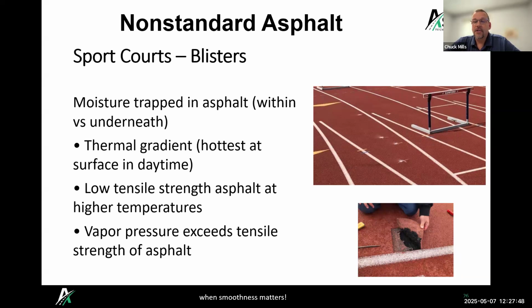So a lot of these coating systems are multi-layered coating paint systems that seal up the air voids at the surface of the asphalt. So if there's any moisture in the asphalt or underneath the asphalt, it can't really escape. And if we don't have proper drainage in the base or the subgrade, so it can escape out underneath, that can build up that vapor pressure inside and cause that bubbling. So again, proper drainage systems is very important because water can cause a lot of problems.